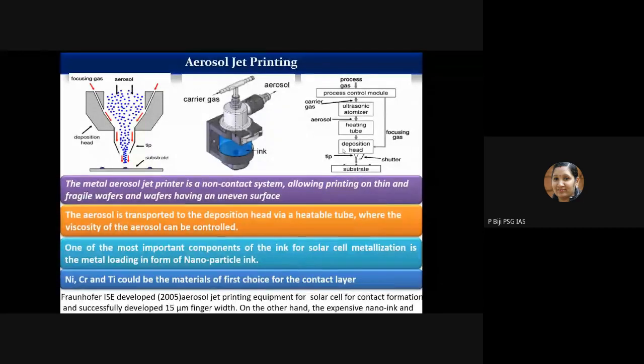In this case, the aerosol is transported to the deposition head via a heatable tube, where the viscosity of the aerosol can be controlled. One of the most important components of the ink for solar cell metallization is metal loading in the form of nanoparticle ink. So nickel, chromium, titanium, etc. could be the materials of first choice for the contact layer. Again, in this case, although this technology is very good for making narrow line width features, up to around 15 micrometers feature size can be obtained very easily using aerosol jet printing.